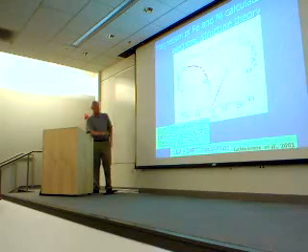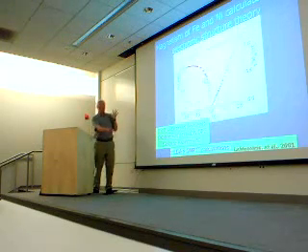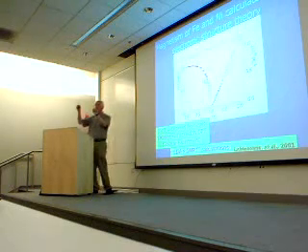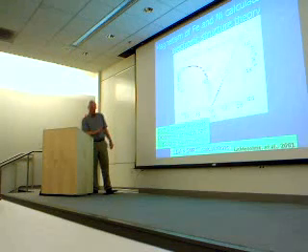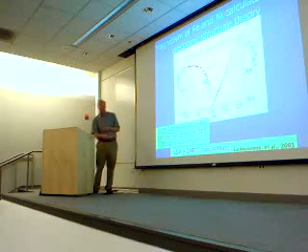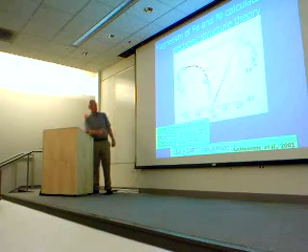If it's not local moments, then every aspect of magnetism goes away when you go above the Curie temperature. But if you still have those moments around the atoms, then they give rise to an enhanced susceptibility. And you learned about that in your textbooks, called the Curie-Weiss law.